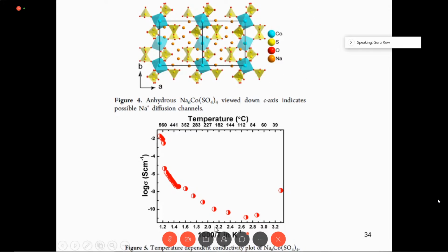So this is the conductivity behavior. As you see, on heating the sample, it loses the surface water, and then at around 120 degrees, it loses 2 water molecules, goes to 2H2O, and then it loses all the water molecules, goes to this particular temperature at which we have the phase transition. The phase transition takes it to a superionic conductor. So the conductivity value now becomes 10 to the minus 2 at very high temperature.